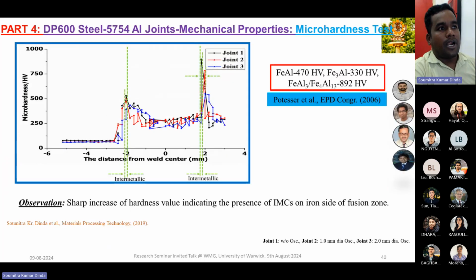And then we did the microhardness, and it's clearly visible: the formation of intermetallics causes a sudden increase of the hardness value in both the HAZ region, or say base metal to weld region, and the formation of intermetallic compounds.